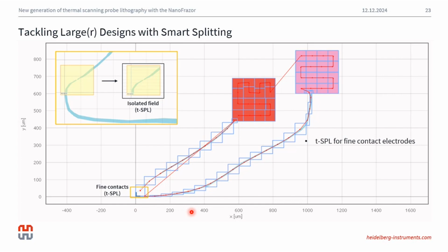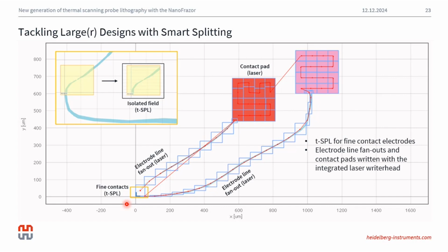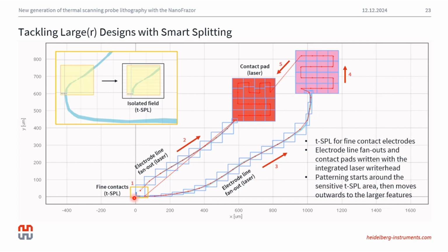This can be a GDS file or a PNG. And we can locally draw a region of interest and tell the NanoFrazor that we want this isolated feature to be written with TSPL or the heated tip, and then assign all the other regions to the laser, for example. And we can also launch the patterning in the order that we want. So typically we start with the very high resolution features here. And then we can very simply tell the tool in which direction to continue the patterning using the laser and finalize the patterning as well.